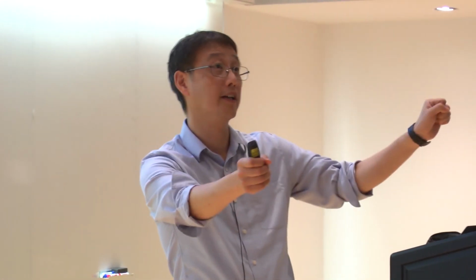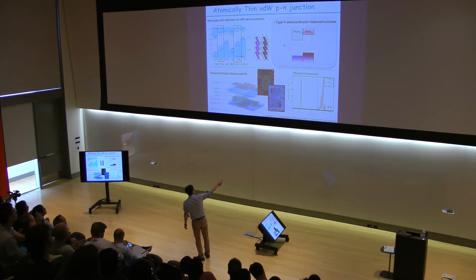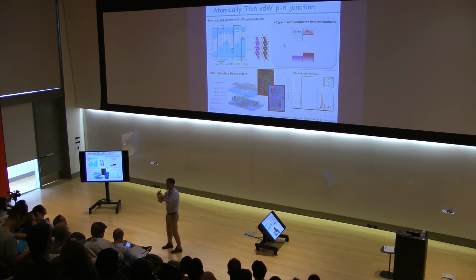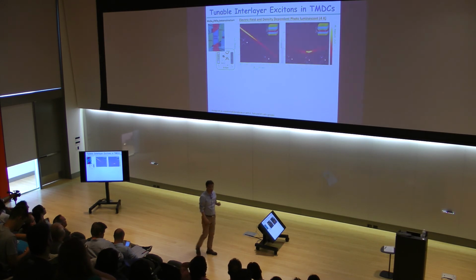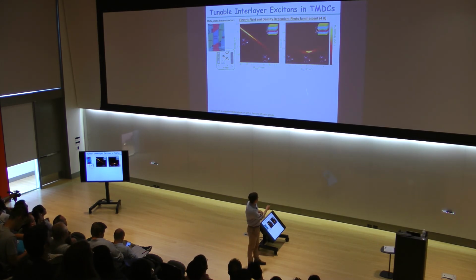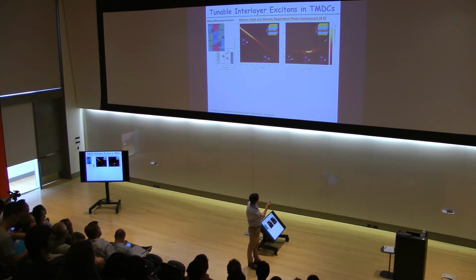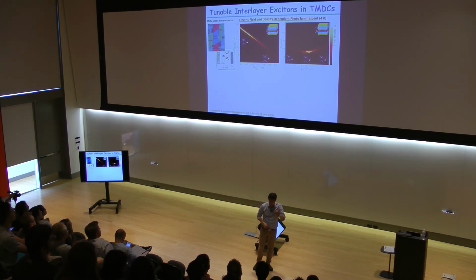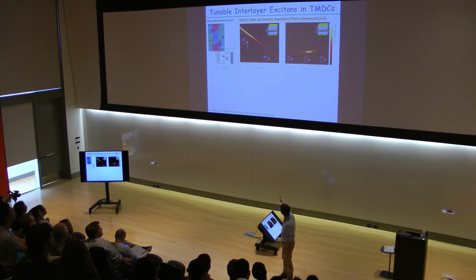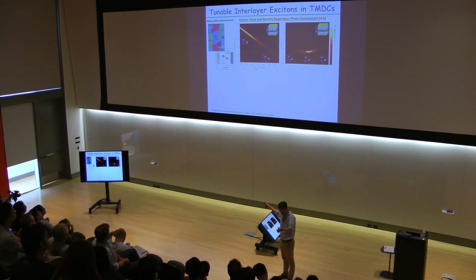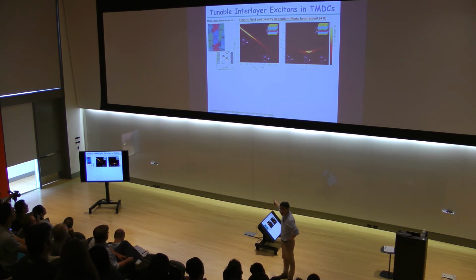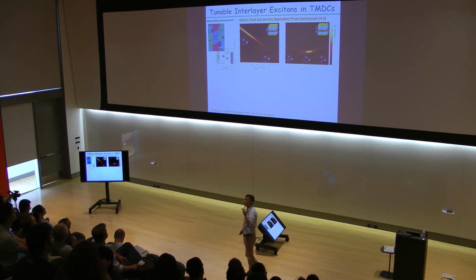I told you that the interlayer exciton can be long-lived in principle because now electrons and holes are separated, right? And on top of that, because this band alignment is not a three-dimensional structure, by just a gate, we can control this band alignment, which means that this energy scale gets changed. Indeed, that's the case. When we show this interlayer exciton peak changes with the gate voltage, again, as you change the density, we see the interlayer exciton energy changes slightly, but outside the gap, we quickly lose the interlayer exciton. So the interlayer exciton only appears when the Fermi level is within the gap. But the important part is, unlike this two-dimensional system, in the atomically thin p-n junction, as you change the electric field by controlling the gate, the interlayer exciton energy is linearly changing, just a linear Stark shift, meaning that the dipole moment is now out of plane.